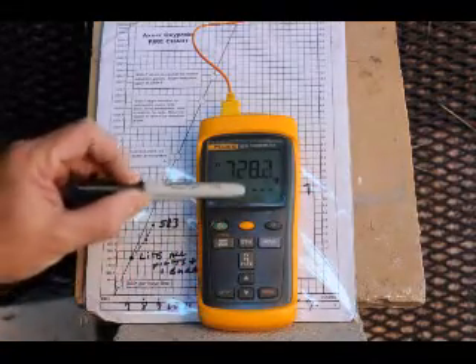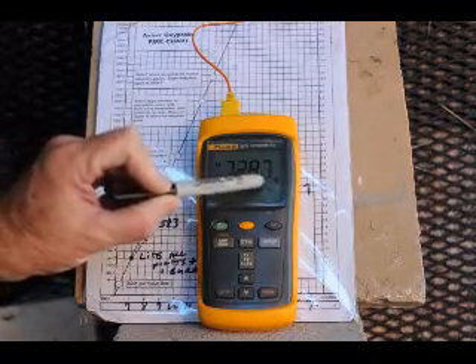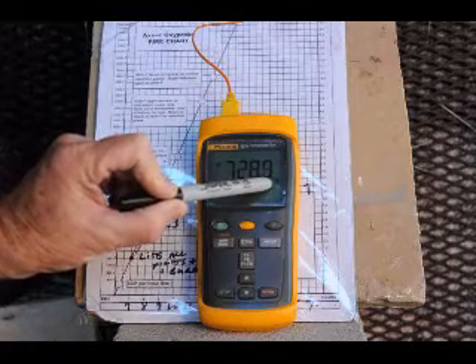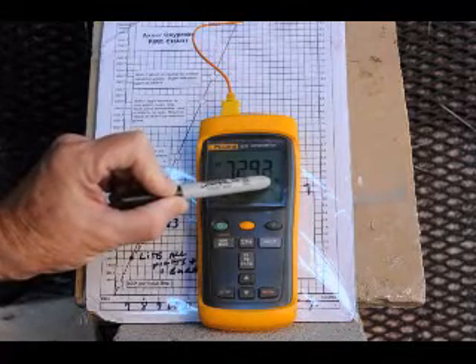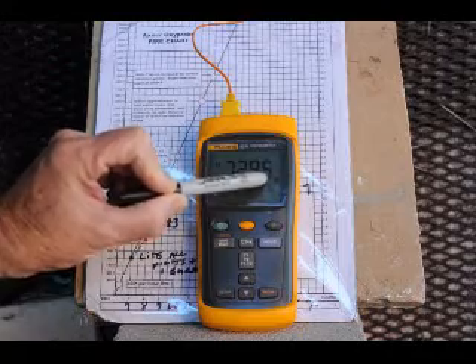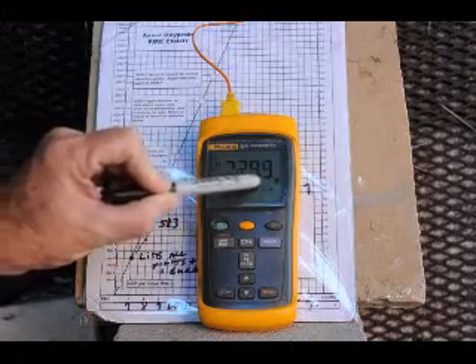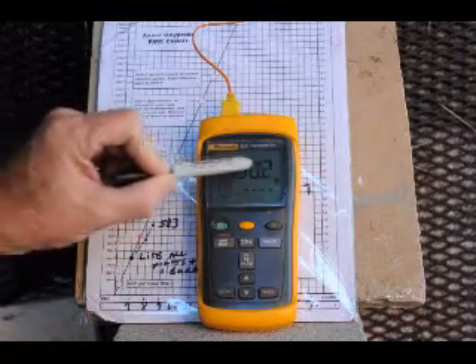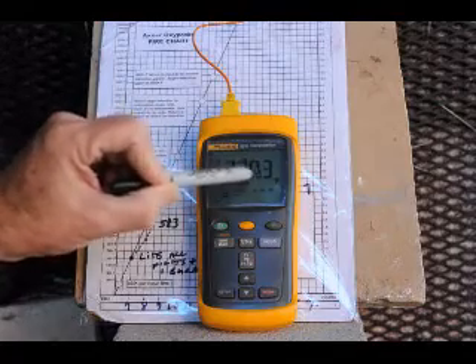Okay, I lighted the 4th burner about 10 seconds ago, and you can see the temperature rise is much more rapid, although not quite as fast as when I lighted the very first burner. So a lot of the energy is now going to maintain this temperature of 730 degrees.